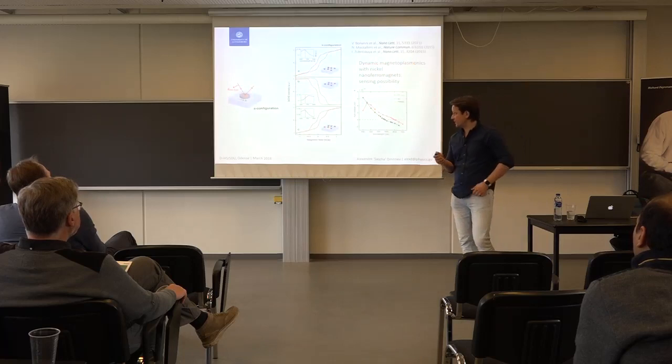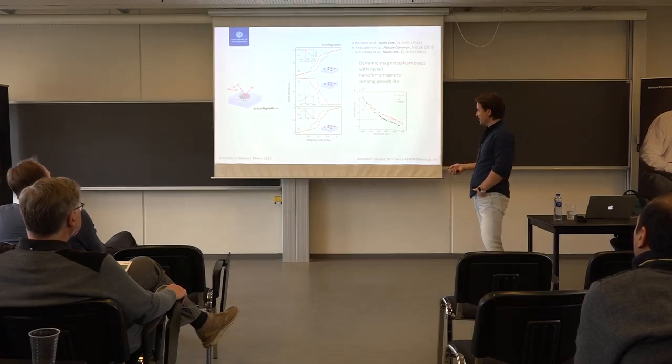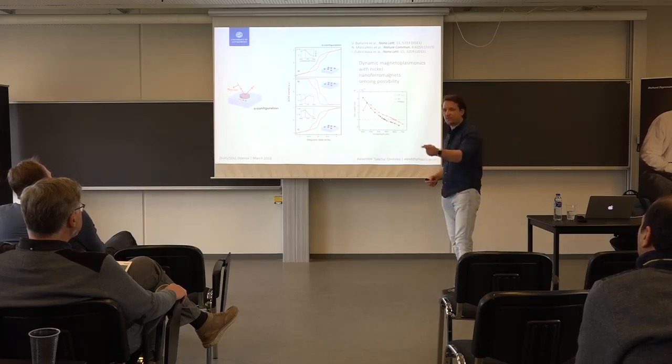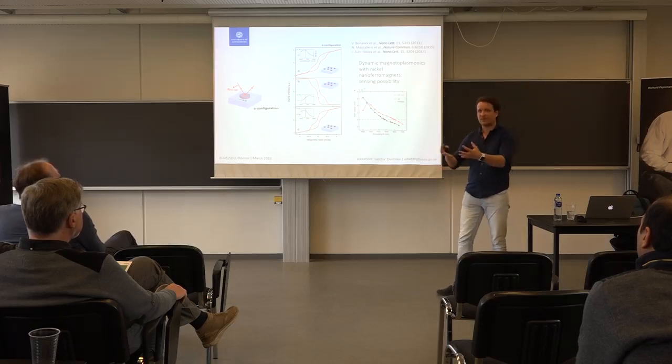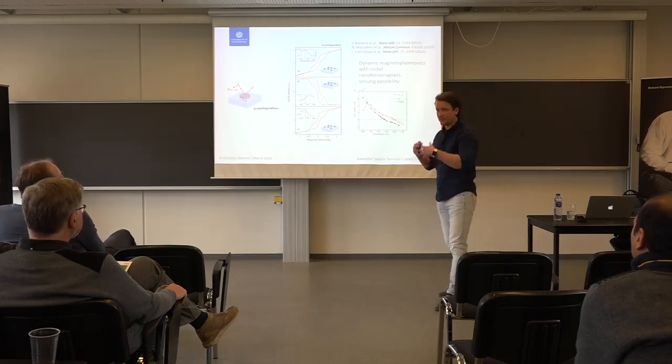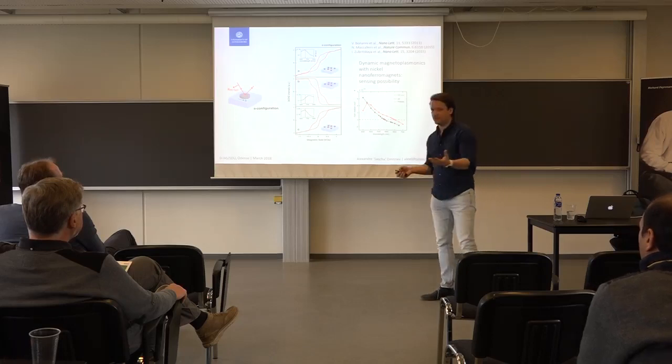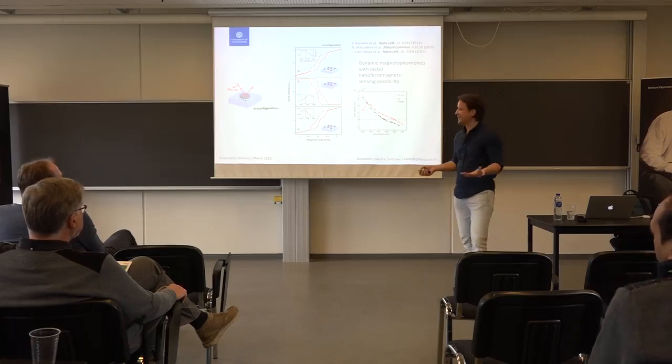And the consequence of that, it's a ferromagnet, of course, we can make these loops, as you've seen before. We can apply a magnetic field, we can measure polarization rotation, except that now the rotation looks really different depending on whether you're sitting to the left or to the right of your plasmon resonance. So you have this extra parameter all of a sudden in the system, this plasmonic response of your antenna. It's not just ferromagnetic anymore. You have this extra thing in your system that makes the magneto-optical response totally unpredictable from first sight. So you can actually change that on the fly.